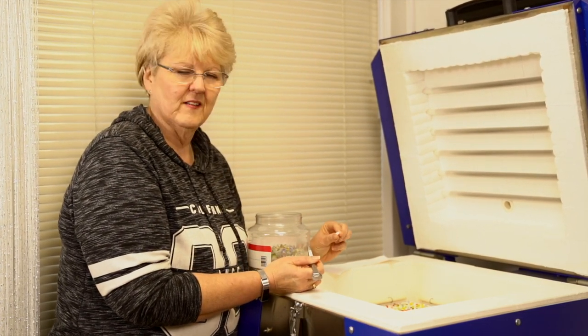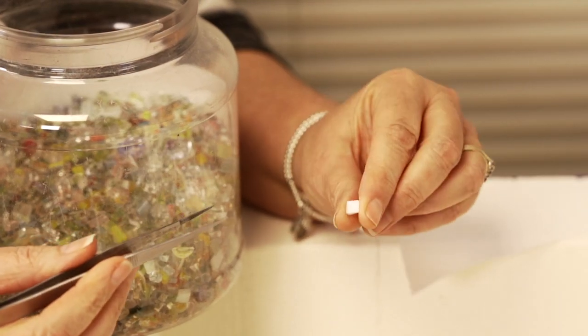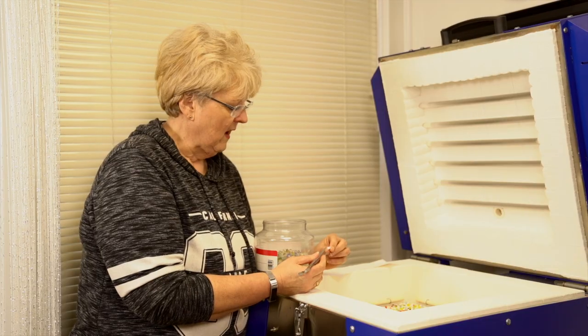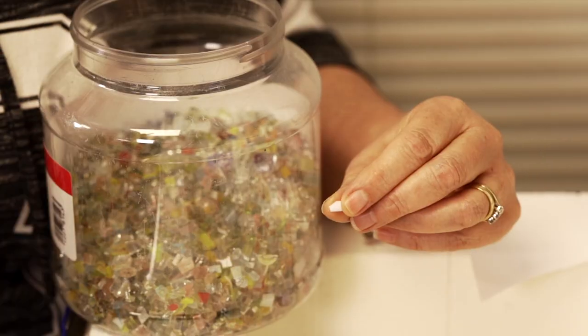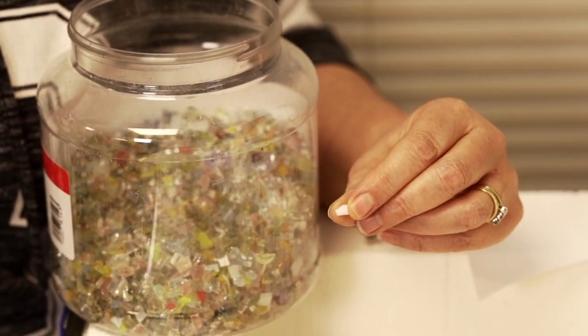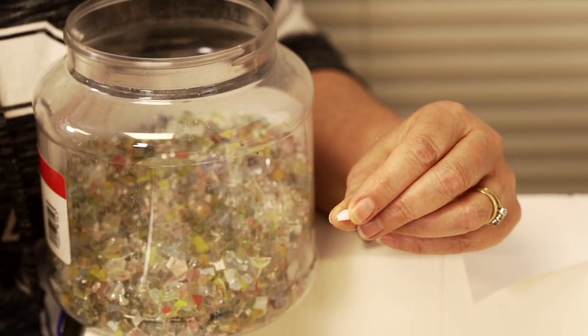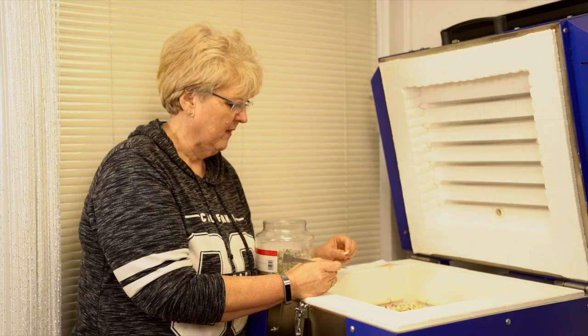The shelf is kiln washed, but if I put opaque beads on that or opaque glass on that, like this kind of stuff. So white is notorious for this, for sticking to a kiln shelf. Once it's fused and become a bead, on the bottom of it, it will lift the kiln wash off. And the only real way of getting that off is probably sanding that off if it's quite severe.